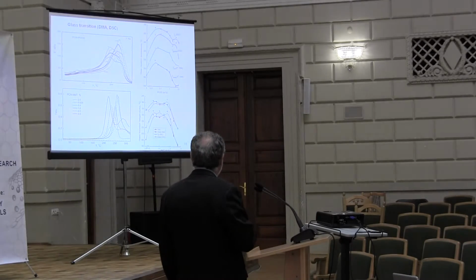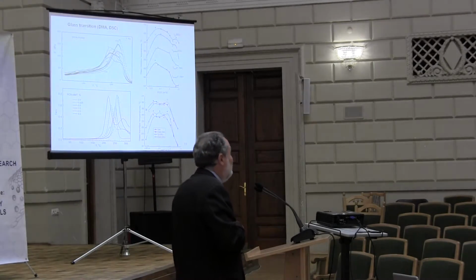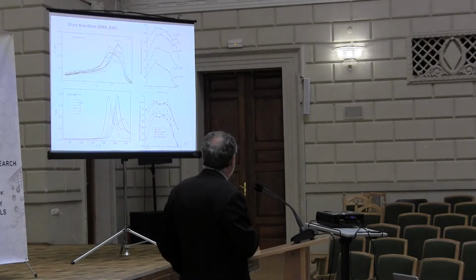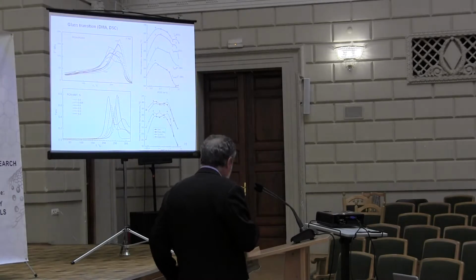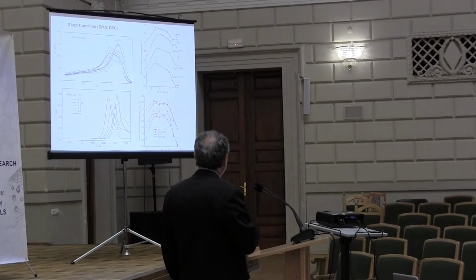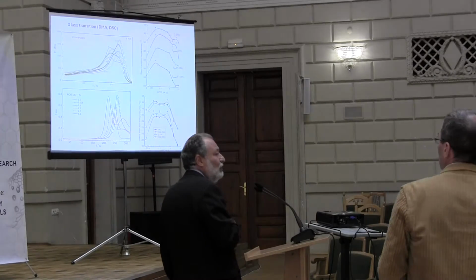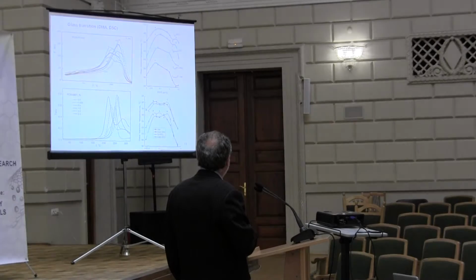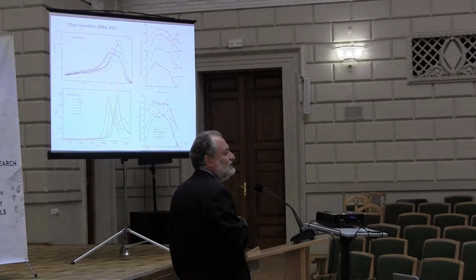And very interesting results we have got with the determination of glass transition temperature for nanocomposites with different amounts of nanofiller. And we can say that we have found the increase in glass transition temperature for the nanocomposites with ultra low amount of the nanofiller. So you see when we add some small amount of the nanofiller, in both cases, we have increasing glass transition temperature. This increase is around 40-50 degrees centigrade.